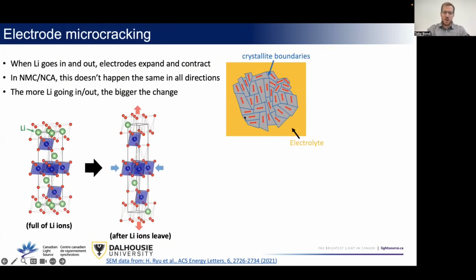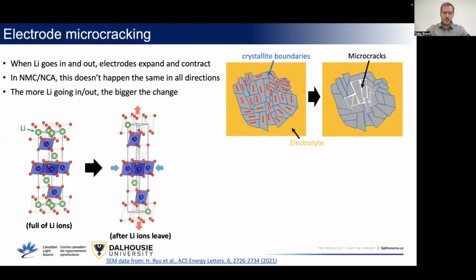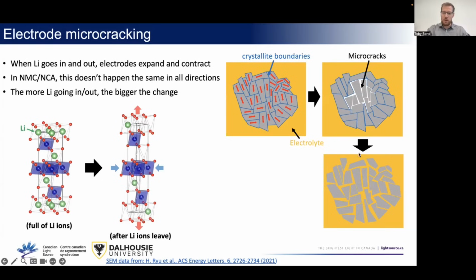If you have one of these secondary particles, one of these snowballs, at different orientations, then you'll get a really complex distribution of stress and strain within the particles. Eventually, after repeated expansion and contraction, that leads to fatigue and what we call microcracks. If that microcracking gets severe enough, it'll actually break open the particle and electrolyte will be able to go inside of it.